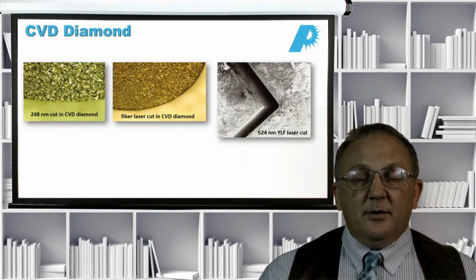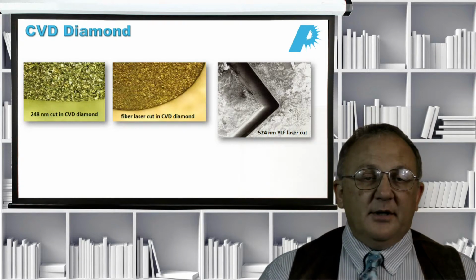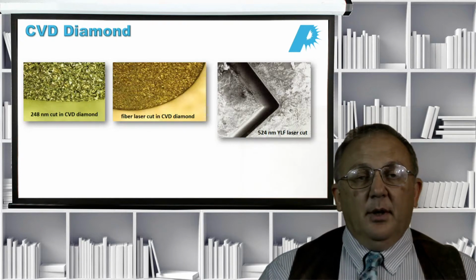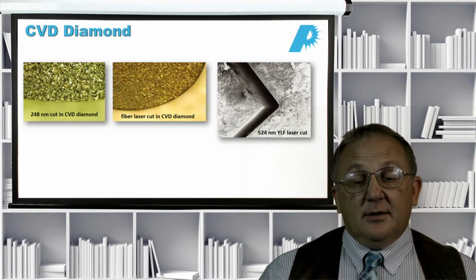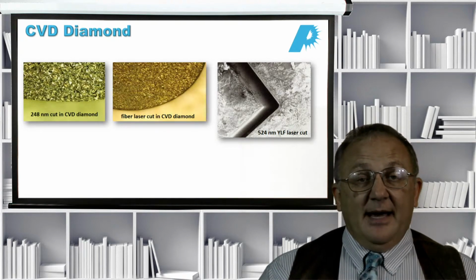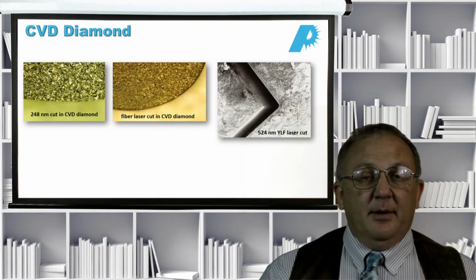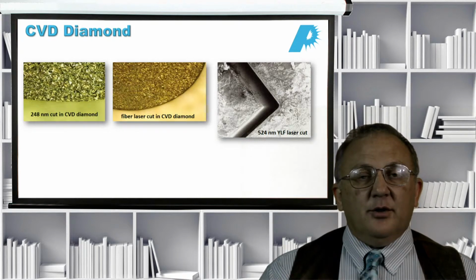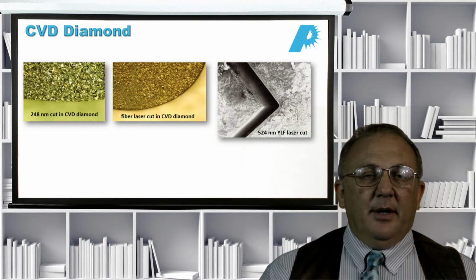In this case, we don't see any evidence of microcracking, microchipping, or carbonization. So in principle, this thing with a very minimal cleaning can be used for applications such as, for instance, heat transfer. In this case, if you've got any carbon between the diamond and the heat generating source, you're not going to have a good heat transfer. So you really want to have diamond butting up against your heat source.